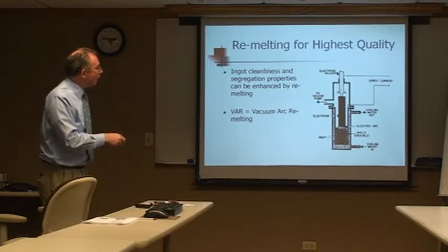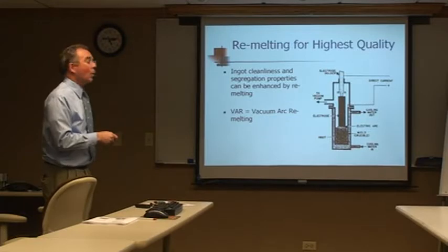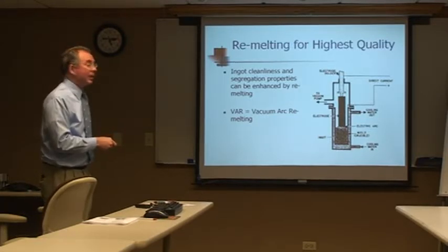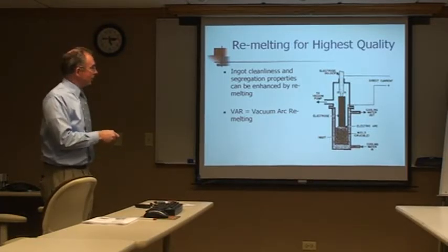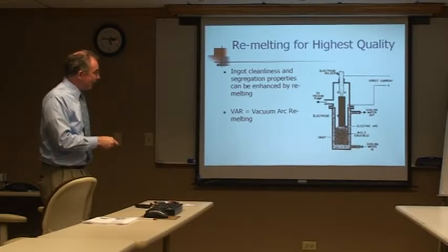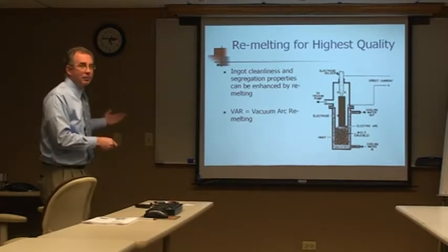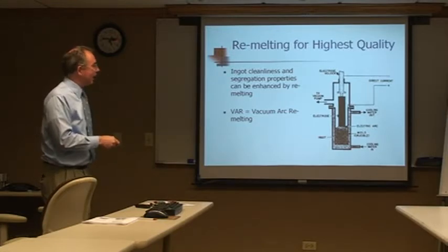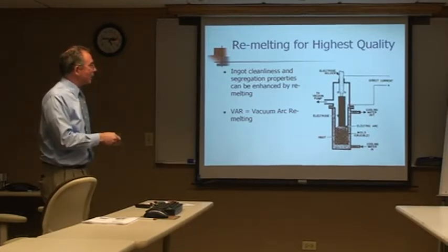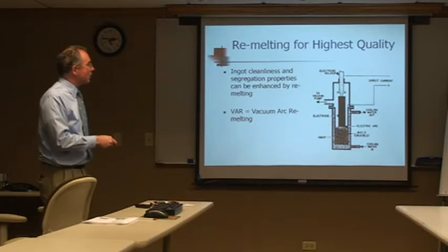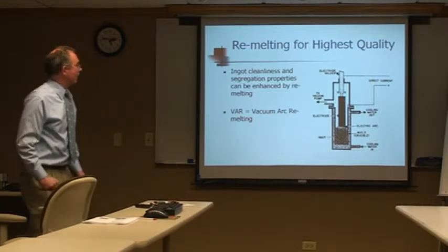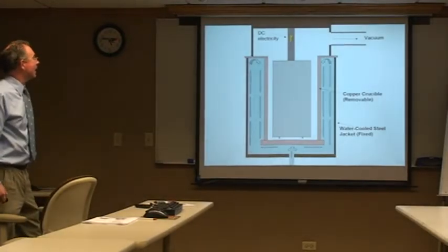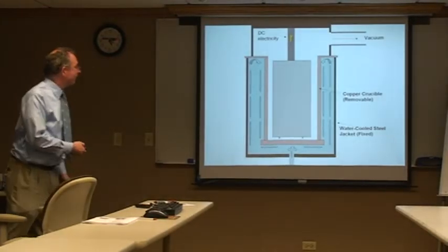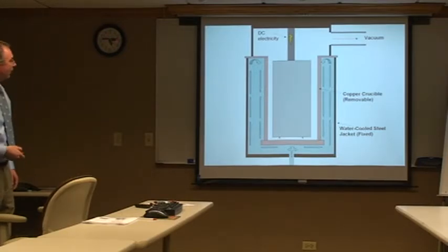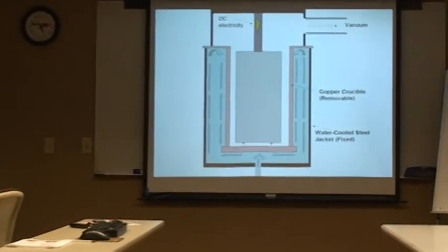And now we're remelting a larger ingot. So if this was a 20-inch diameter ingot, we might remelt it into a 24-inch crucible. So the 20-inch air melt ingot gets remelted to a 24-inch, as an example, VAR ingot. And again, drop by drop. This electrode is melted until it's completely consumed, and it is reformed as this VAR ingot. And our man Dan has done another great VAR simulation. So let's see how it works.